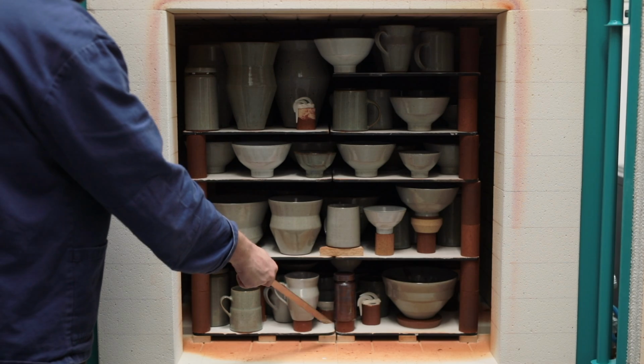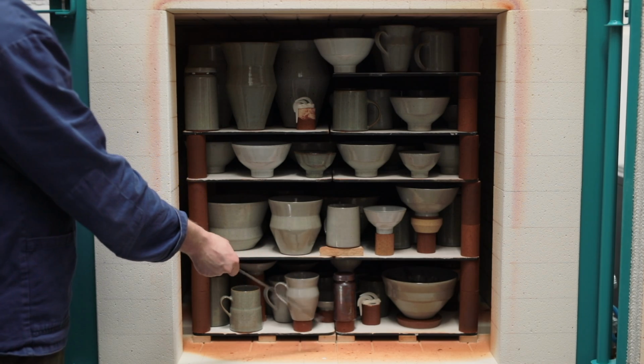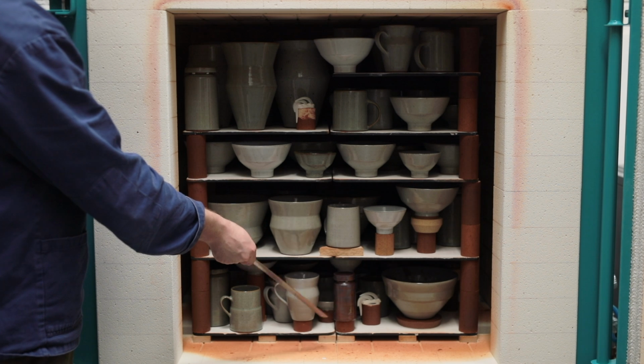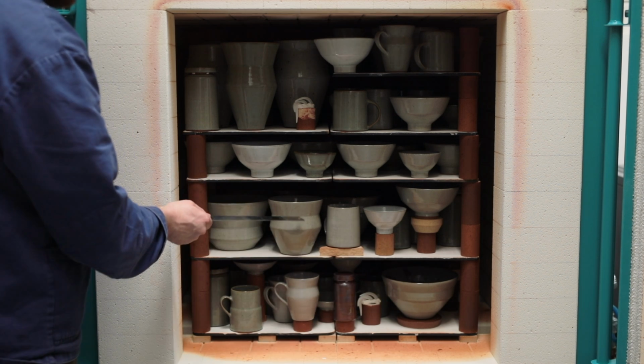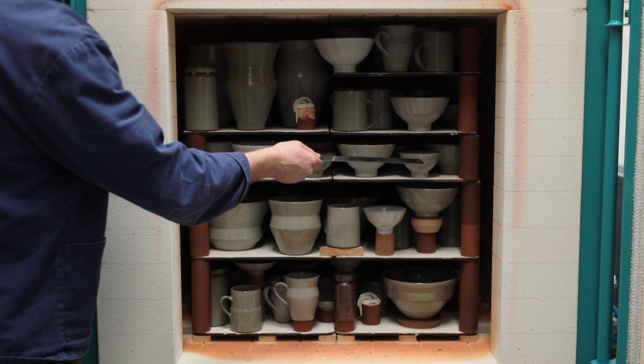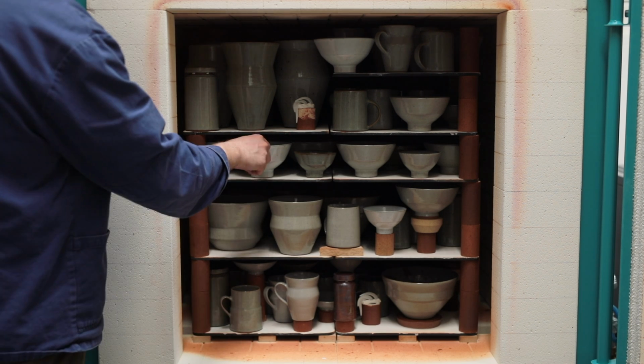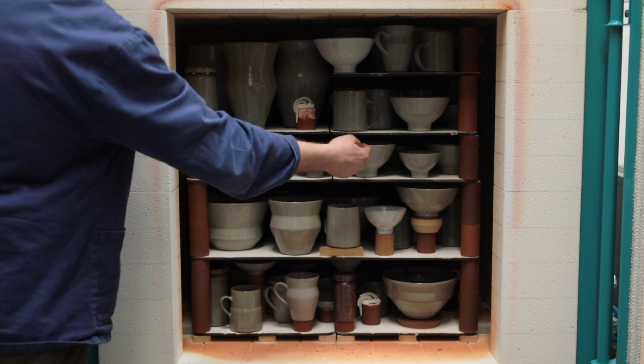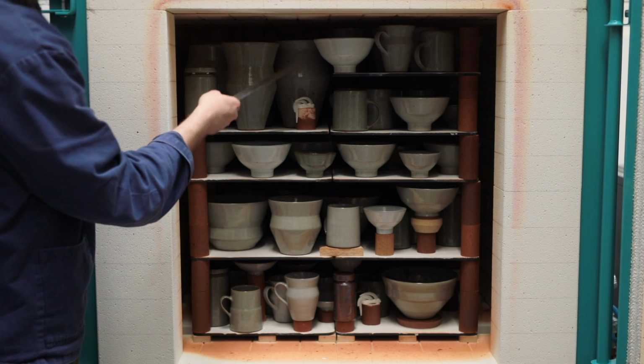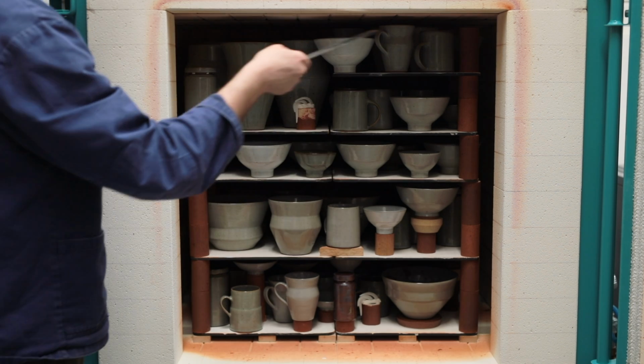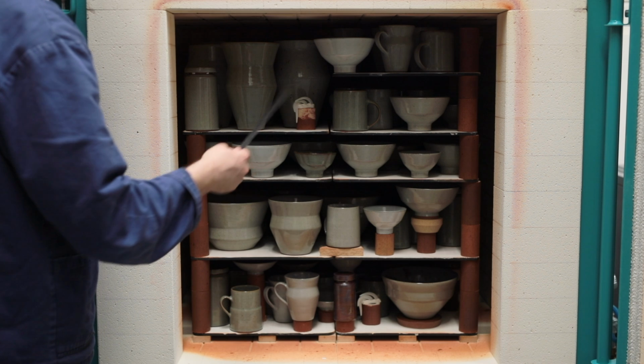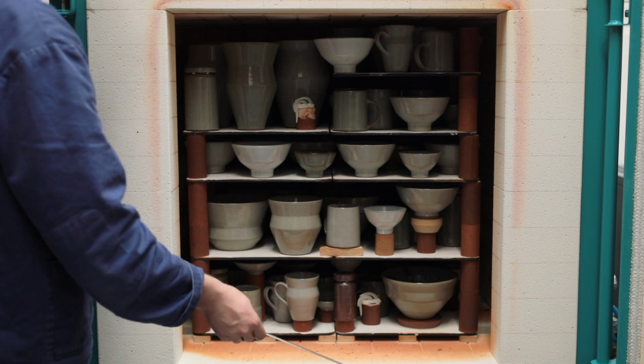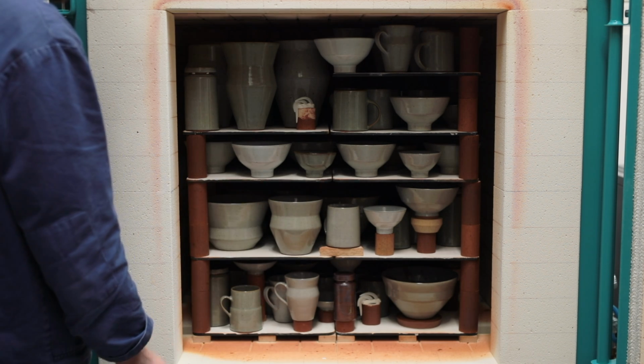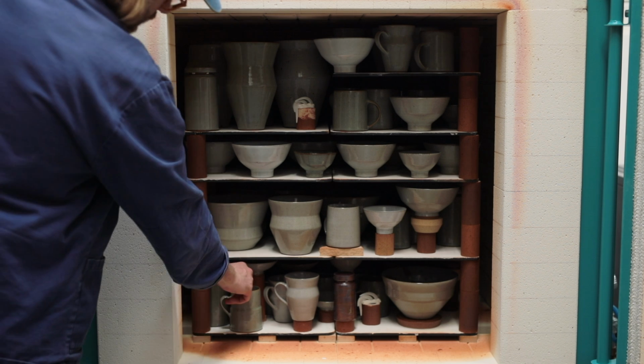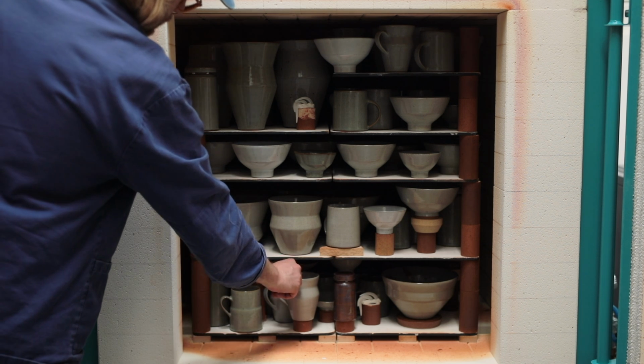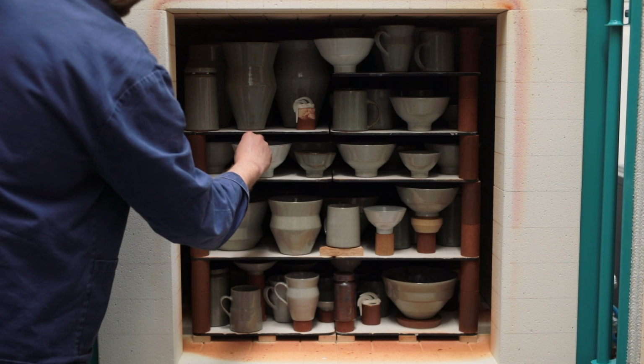Typically, the bottom, especially at the front, will under fire slightly, resulting in some of the glazes having a matte quality to them, and this can even spread up the pots at the front, as during the firing when the door is closed, these pots are essentially right next to a wall that comes into contact least with the flames. So inevitably, I expect there to be a few cool patches. Heat rises too, meaning the pots at the top will always be fired to a slightly higher temperature. This also means that whilst I can touch the pots at the bottom, now those at the top are still very hot.